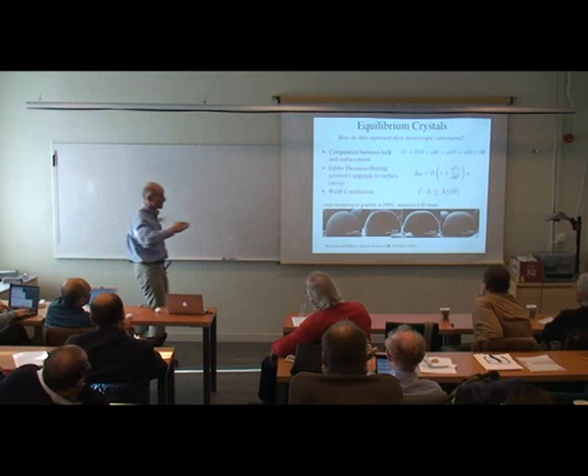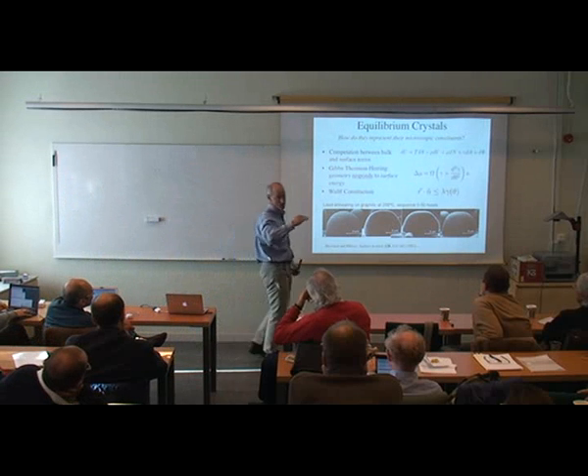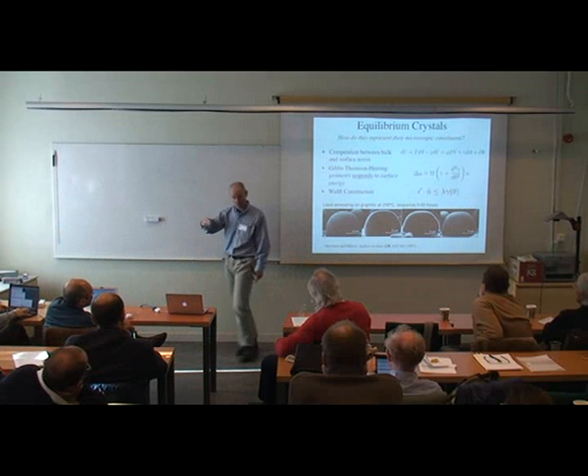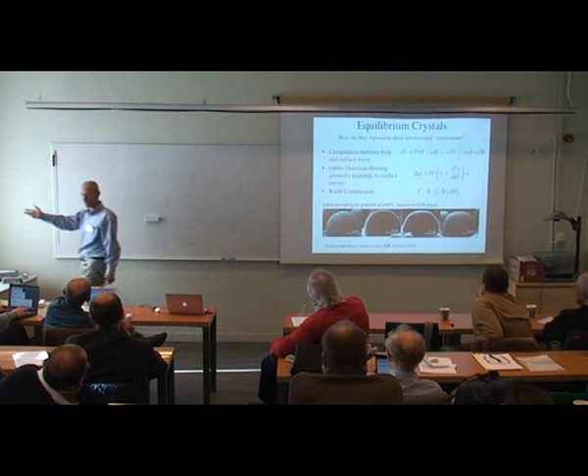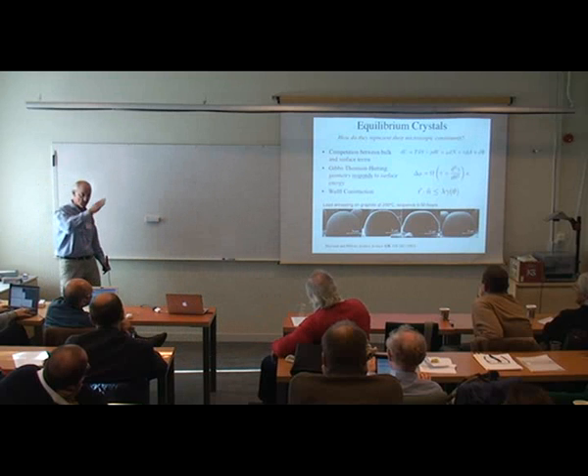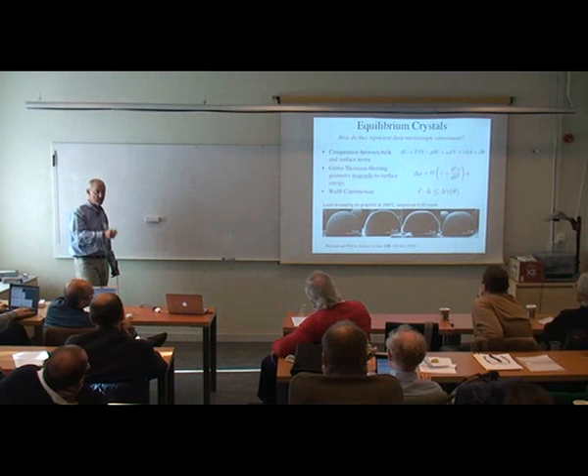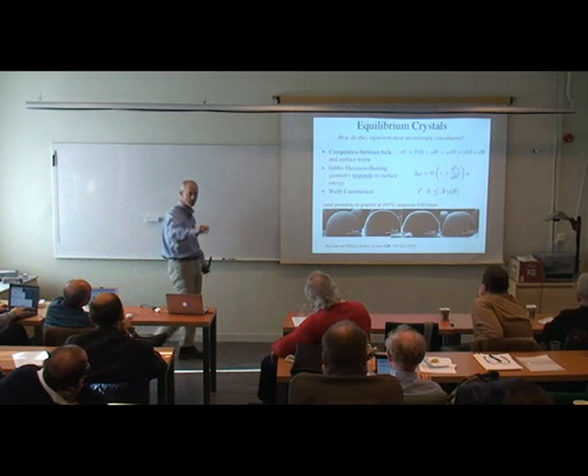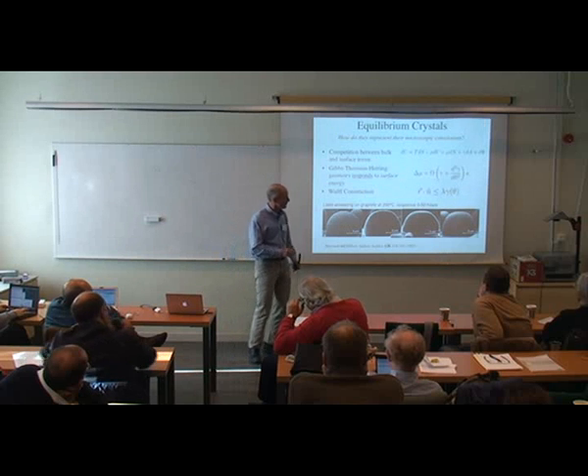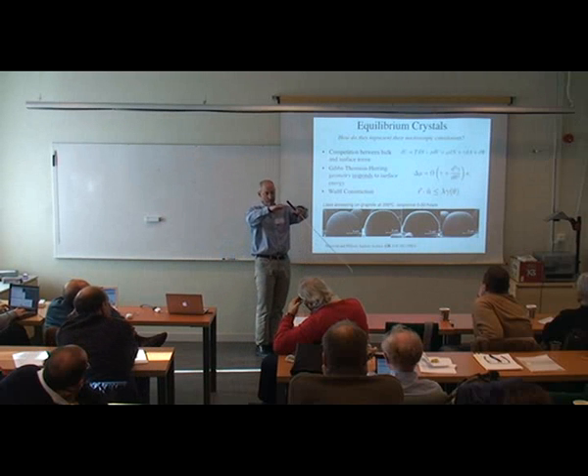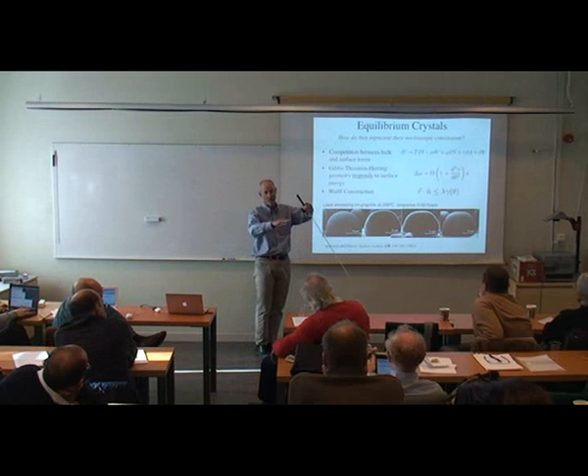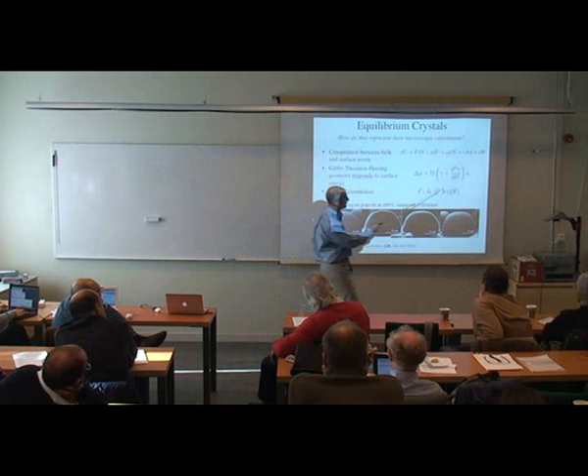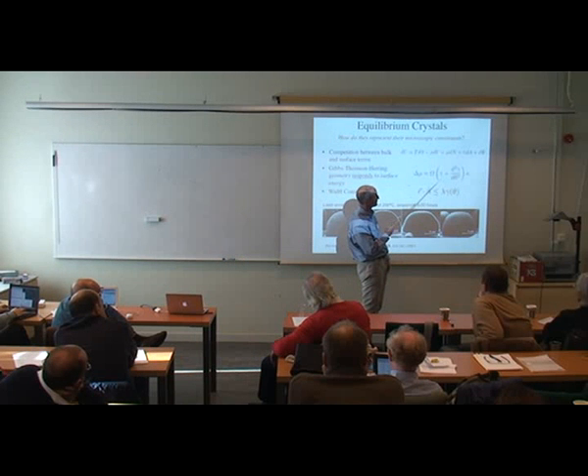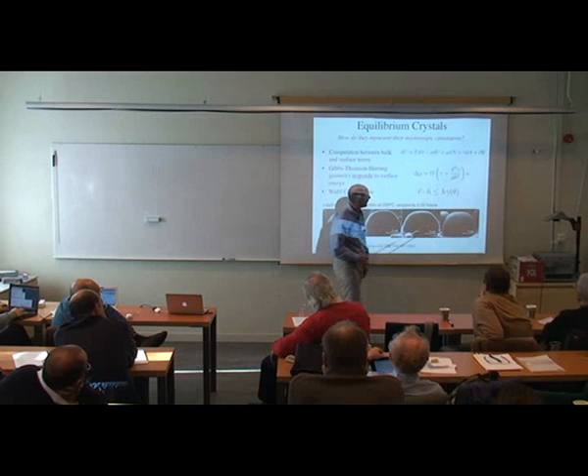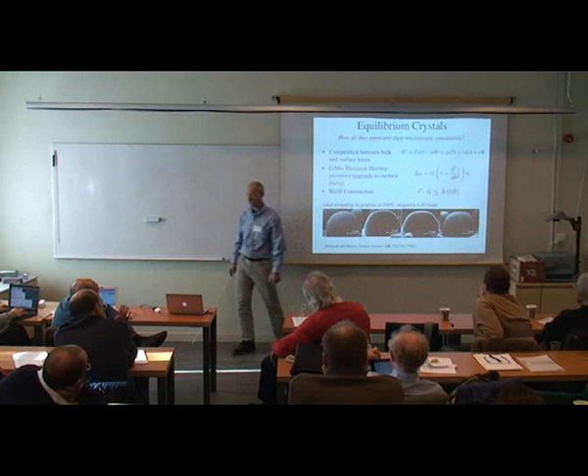So then the surface tension is replaced by a surface free energy, still obviously extensive with area, in the same units, but it depends on the angle at which you prepare the surface. It's the energy it takes to break the bond per unit area, modulo the irreversible work, plus the energy it takes to torque the surface. And that gives you a surface stiffness, which is the sum of these two things. So this may be familiar to you. This assumes small angles, or does it work generally?